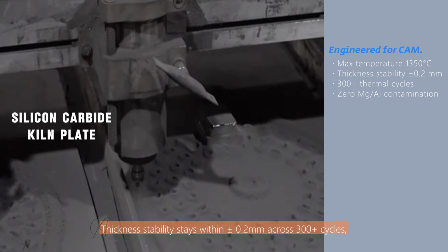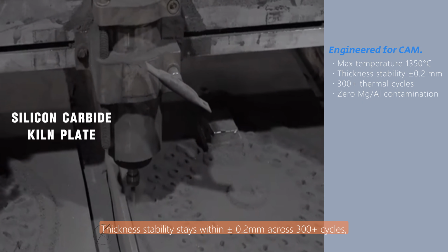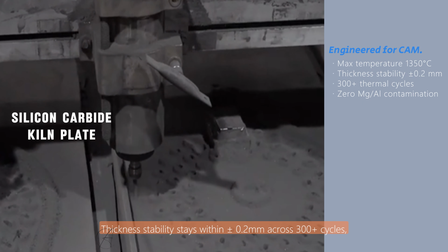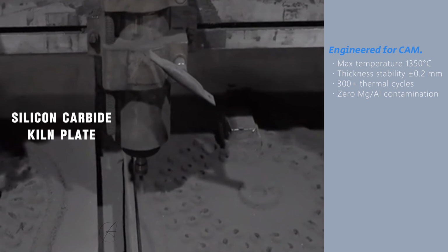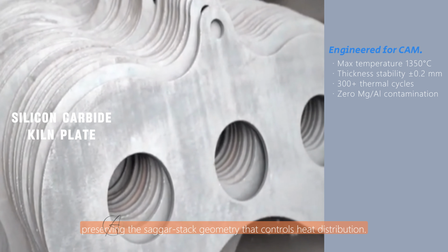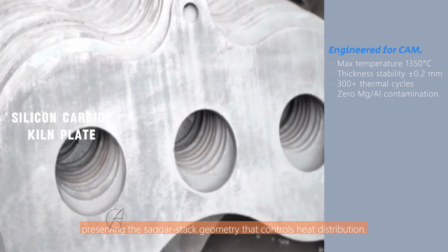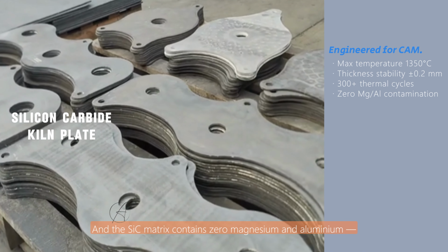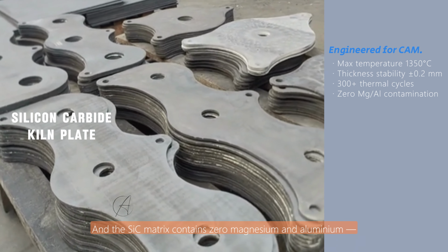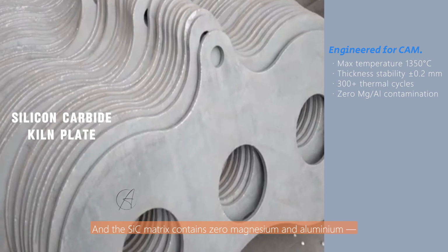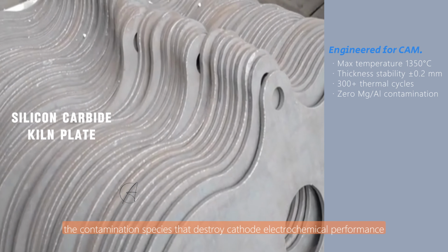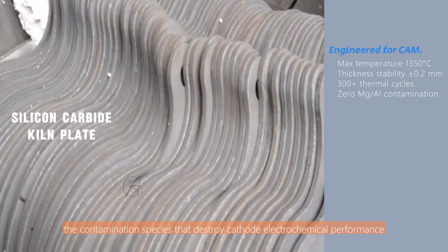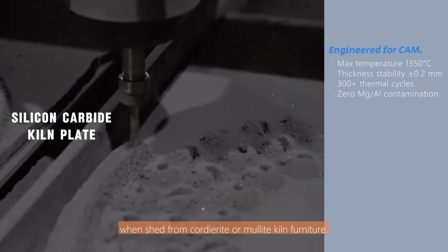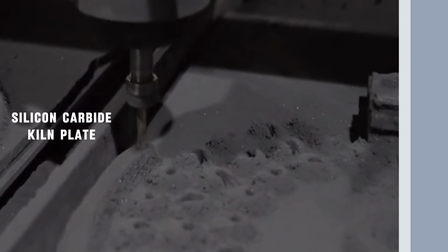Thickness stability stays within plus or minus 0.2 mm across 300 and more cycles, preserving the saggar-stack geometry that controls heat distribution. And the silicon carbide matrix contains 0 magnesium and aluminum, the contamination species that destroy cathode electrochemical performance when shed from cordierite or mullite kiln furniture.